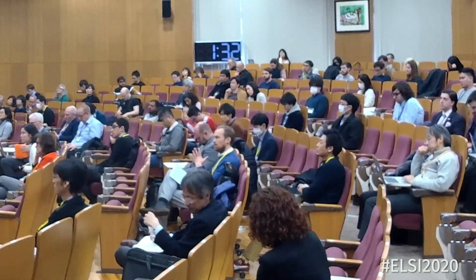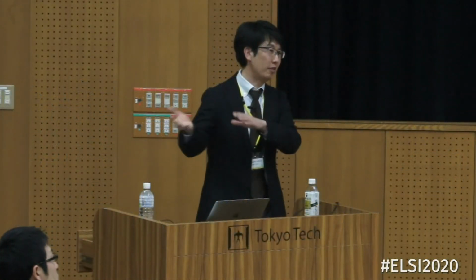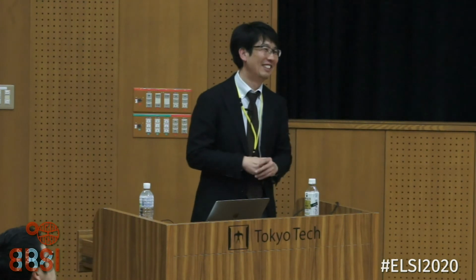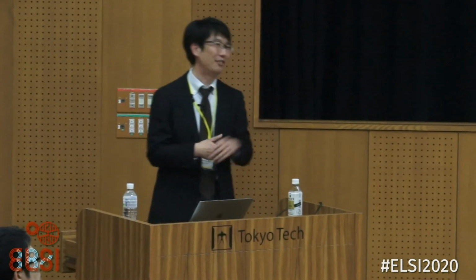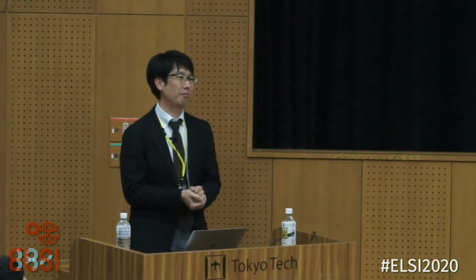Right. That is a very, very important part of designing this kind of composite. We enforce the stability of the protein crystal by using cross-linking treatment. After the soaking and deposition of the metal complex using organic solvent, we completely remove the excess metal complex, then dry completely under vacuum. But after coming back to the buffer solution, we can still get diffraction from the crystal when we use the lysozyme crystal. Of course, we have tried different types of crystals from different proteins and never got diffraction data. That's why the first important thing is which protein crystal is utilized as a scaffold. Right. Thank you.